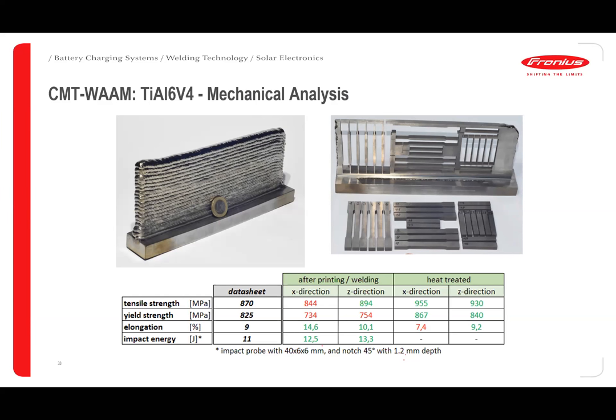So this gave us a very good confidence that though the microstructure was showing some kind of alpha prime, a martensite kind of structure, we will be able to achieve mechanical properties which will be better when we do the heat treatments. And this gives us a very high confidence that we can use this alloy for various other actual applications, commercial applications also.